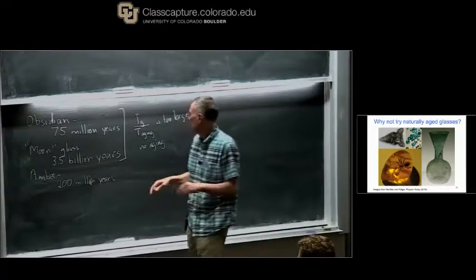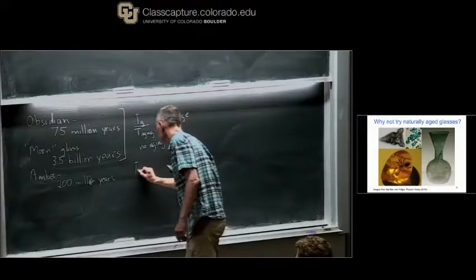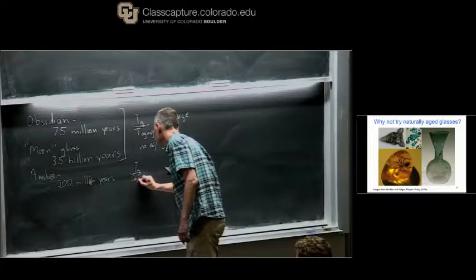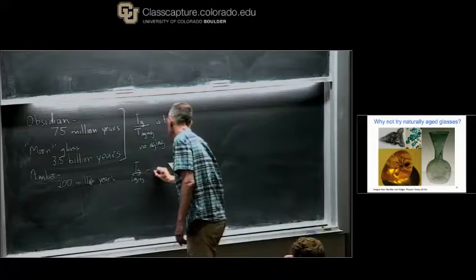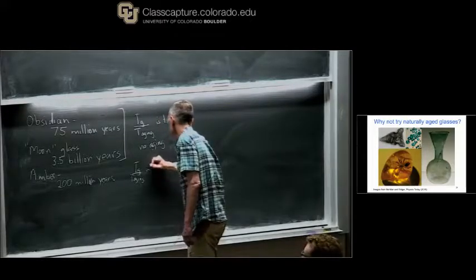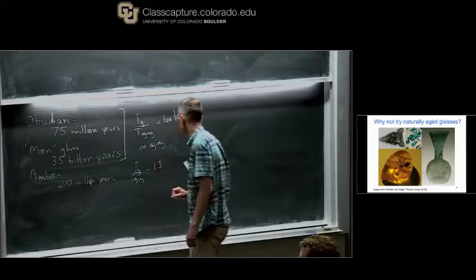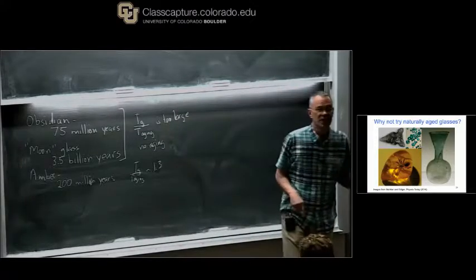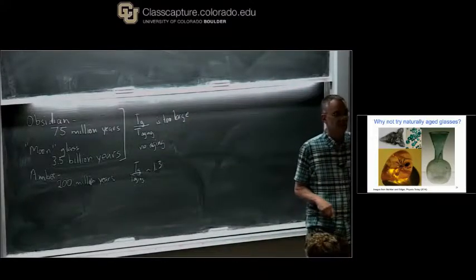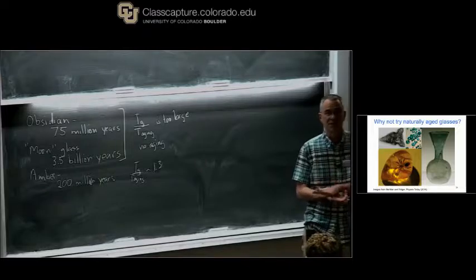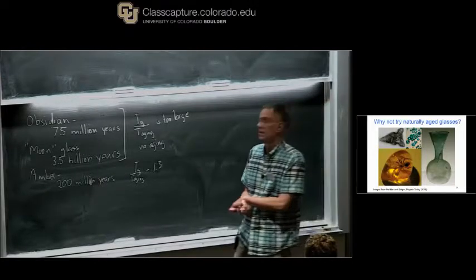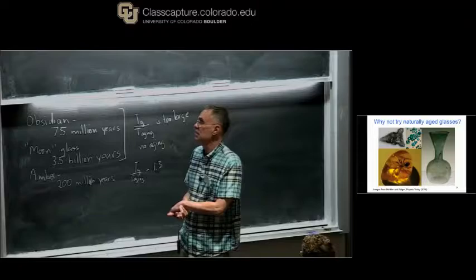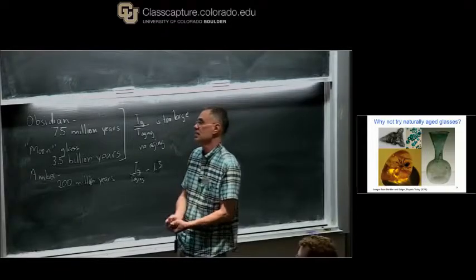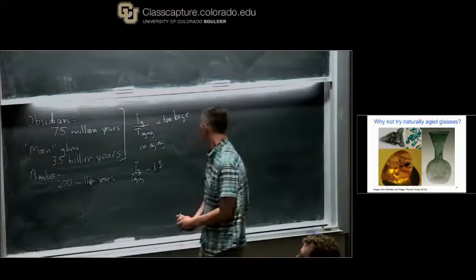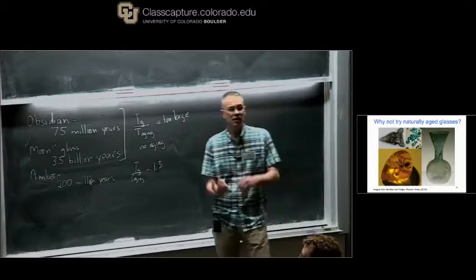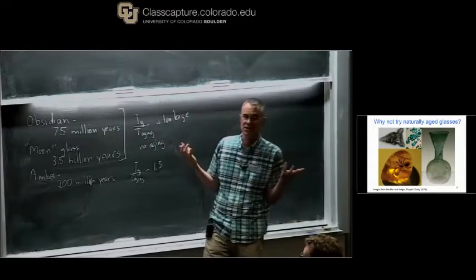Amber, here Tg over T aging is something like, let's see, 1.3. And so this is close enough that a lot of aging can happen. And so there has been some nice recent work using ambers to try and understand what happens deep in the energy landscape. Greg McKenna's done this. Miguel Ramos has done this. And so far they've looked at ambers from 10 different sources.